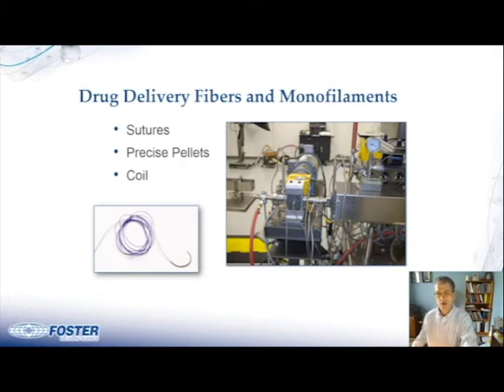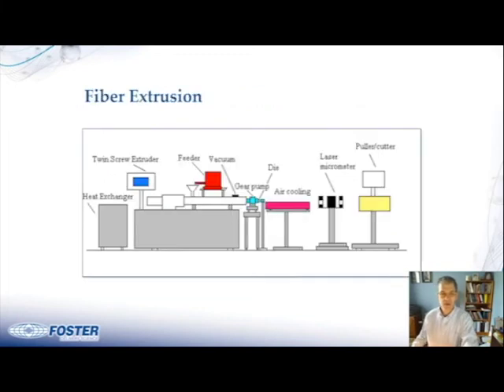So I have a schematic of this process. So you have the twin screw extruder, you have a gravimetric feeder into the feed hopper, the twin screw extrusion process, and then a gear pump that's attached to the machine as shown in the previous picture. And then custom cooling devices that are used. There's air cooling, a laser micrometer for precise dimension control, and that's followed by a puller/cutter.